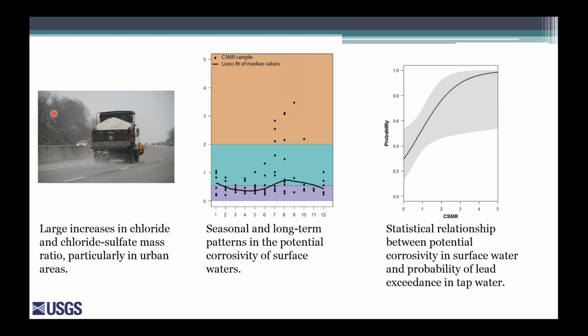Yeah, that's a good question. I think the idea is that the phosphate is much more effective, and the reason the phosphate is more effective is that it creates a passivation layer on the inside of the pipe, and it's a relatively stable passivation layer. And so lead phosphate is a pretty stable compound, and it will stay on the insides of the pipes. That said, drinking water facilities do add sulfate to drinking water, but they don't do it for corrosion inhibition.